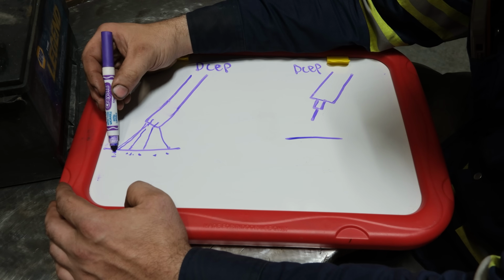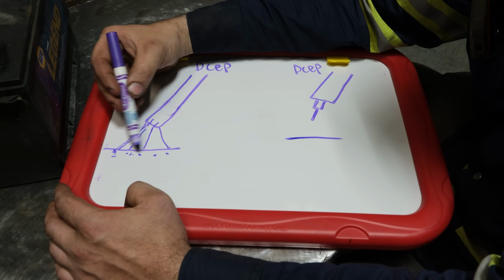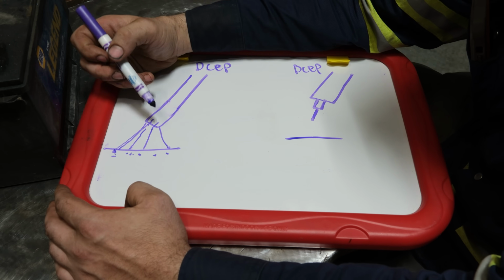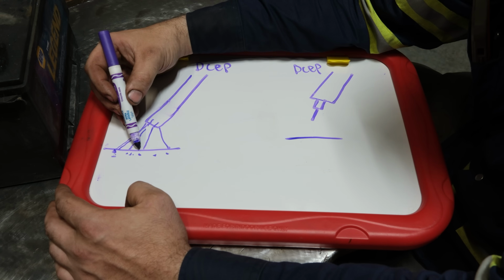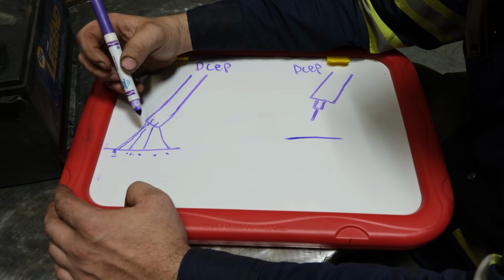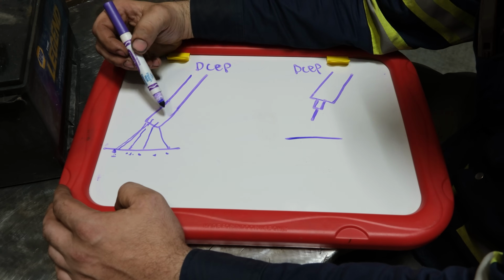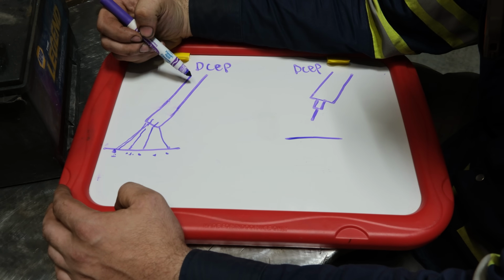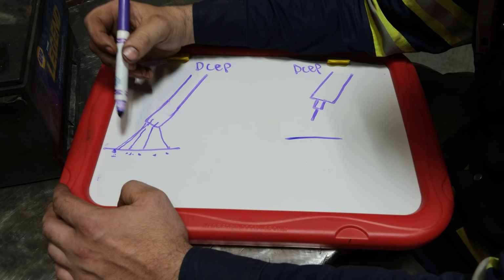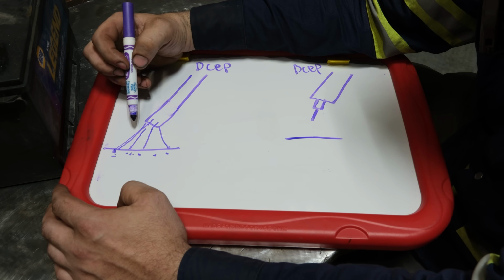Your arc will now wander to there. So you get a lot more arc wandering, I think, on electrode positive than you would on negative. And interestingly enough, you actually can stick weld on electrode negative. What you would find is a quieter arc.